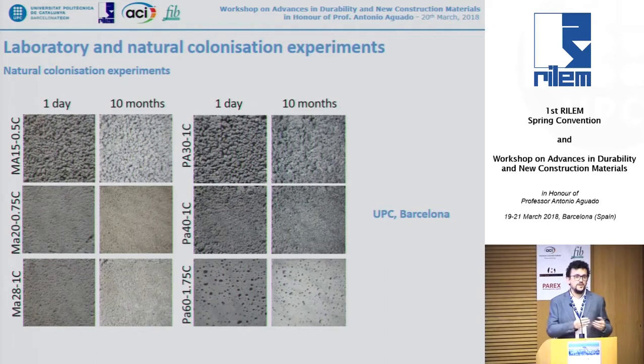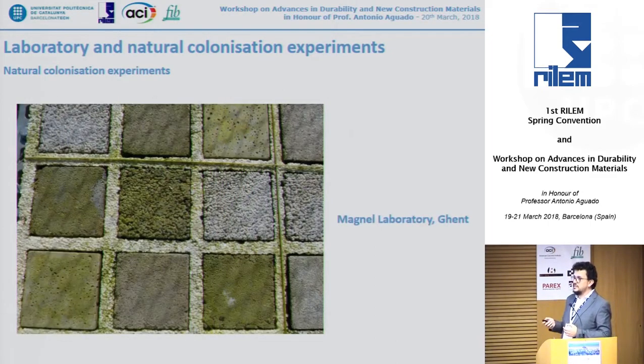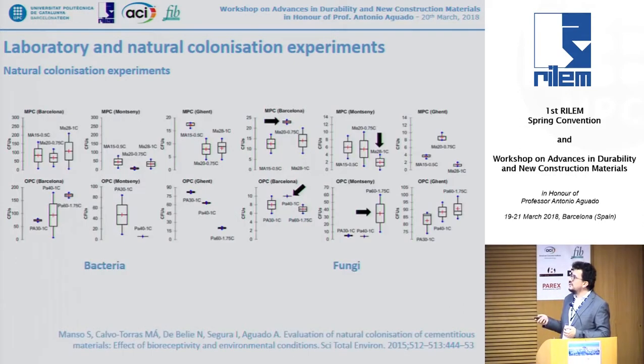Unfortunately, we had very good results in the lab. We have a very high and early colonization of our samples, but after 1 year of exposure to the natural conditions, we almost did not see any biological colonization. That was in Spain. Again, we see a little growth of algae on the surface of the samples, but in fact, the biological colonization of the samples was not very significant, and there were not significant differences between MPC and OPC samples. We did have very small differences.